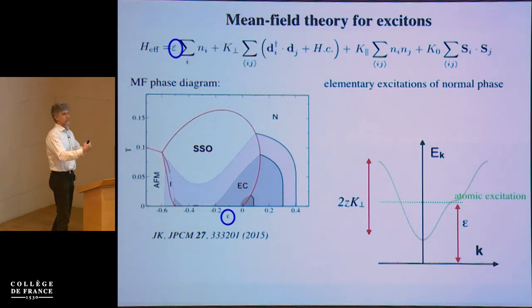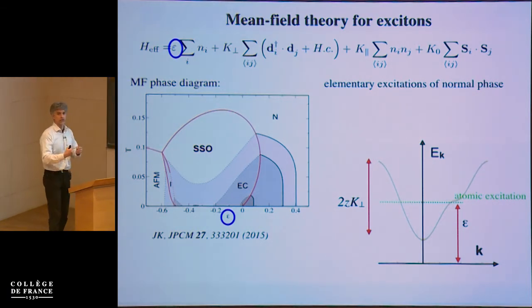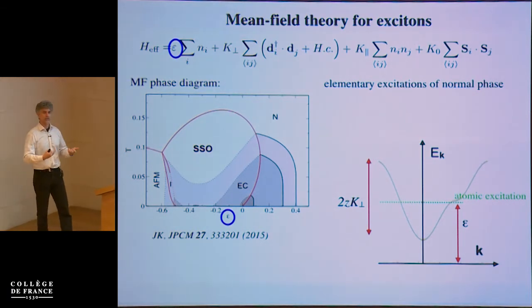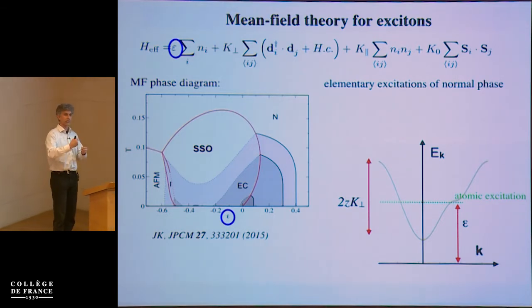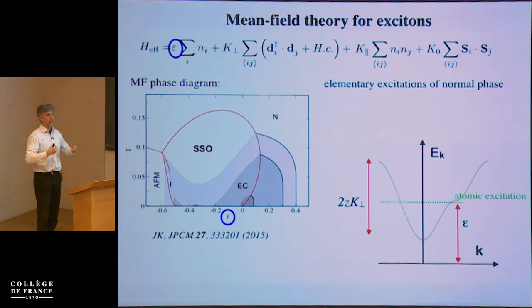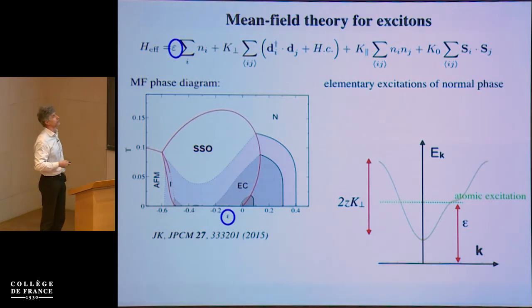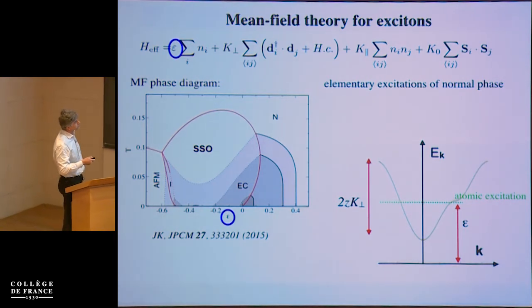and this nearest neighbor repulsion term is dominant, we will get a crystallization. So we will get a high spin, low spin, high spin, low spin order, which is essentially a crystal of the high spins built on this low spin vacuum.